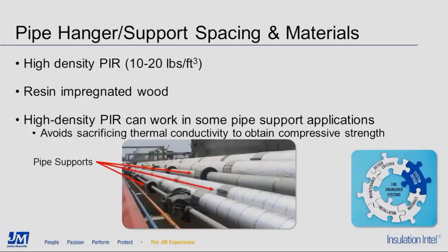The next key design aspect is pipe supports. Insulation must be used at pipe supports, and this can take many forms. On rare cases, super strong resin-impregnated wood is used, but this has very poor insulating ability. More commonly, high-density polyurethane is used at the supports, and this can range in density from, say, 10 to 20 pounds per cubic foot, with a higher density having much higher compressive strength, but also having comparatively poor insulating ability versus the neighboring PIR insulation, or cellular glass insulation.